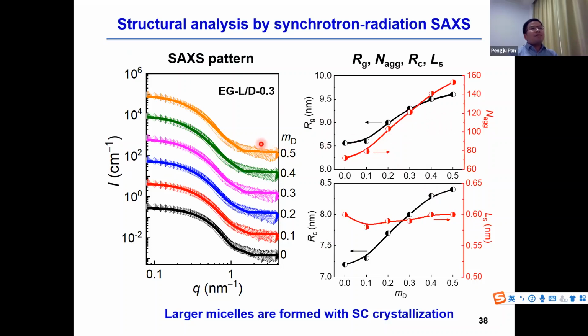From the SAXS analysis, we know the gyration radius, aggregation number, and core radius of the micelle increase after the stereocomplex crystallization. This means the stereocomplex crystallization between the L and D block can associate more copolymer chains in one micelle and lead to the formation of a larger micelle.